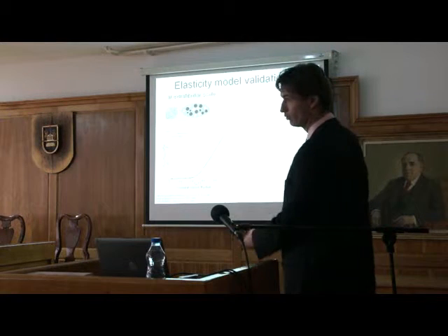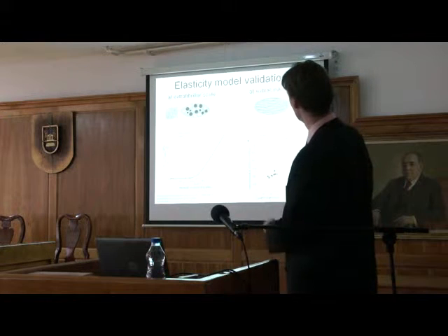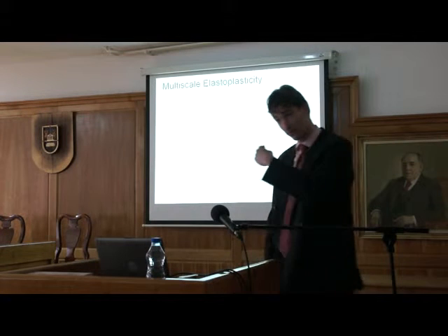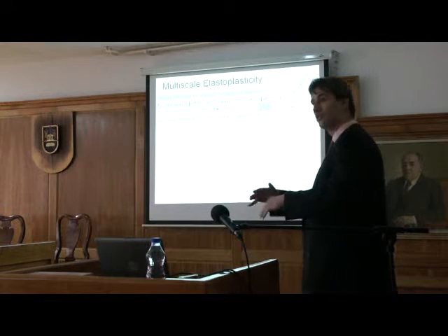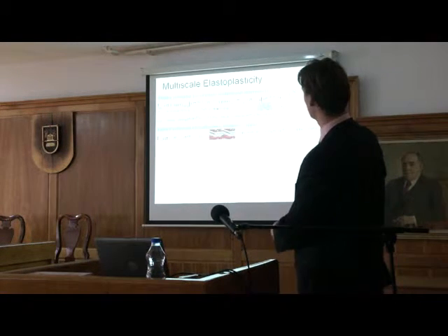If the points are on the curve, it's good. If not, it's not good. And this is at this scale, and we did a lot of different other things. And before I stop with this, we went one step further. This was elasticity. Now, if you go to elastoplasticity, we say, okay, the crystals are glued together. There's water in between. Once we have a certain limit surpassed, then they start to glide on each other. And the more the crystals glide, the more load comes to the collagen, and the collagen would fail as a Rankine criterion, so brittle. Collagen, there is no chance for plasticity.